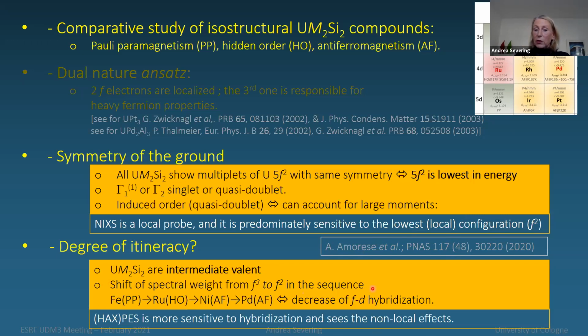However, the photoelectron spectroscopy is sensitive more to the hybridization effects and therefore sees more the non-local effects. So we are seeing the local effects in NIXS and we're seeing more the non-local effects in HAXPES, and that we think fits very nicely with this ansatz or concept of dual nature of 5f electrons. This was a concept from Gertrud Zwicknagel and Peter Thalmeier that they developed for these heavy fermion compounds, that two of the electrons are localized, and it's the third one that is more itinerant that is responsible for the heavy fermion properties.